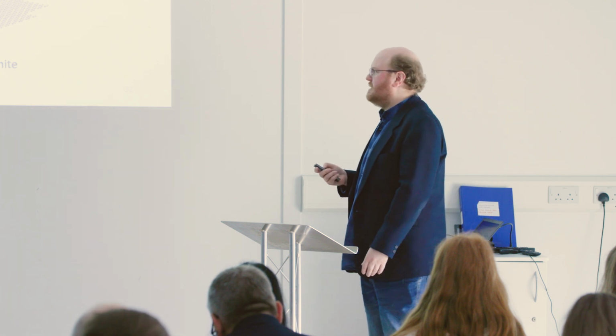I also said in terms of the way we produce this, our group does a lot of work on electrochemical exfoliation. It's a very popular way to do it. It works essentially like a lithium-ion battery does, where you take graphite, which is used as an anode in batteries, you apply a potential in an electrolyte, and you basically get these ions that force their way in between the layers. That expands the interlayer spacing. If you keep on applying potential, you keep on forcing more and more ions in there, or larger ions in there, you basically push these layers completely apart.